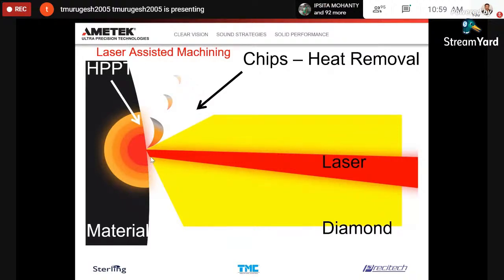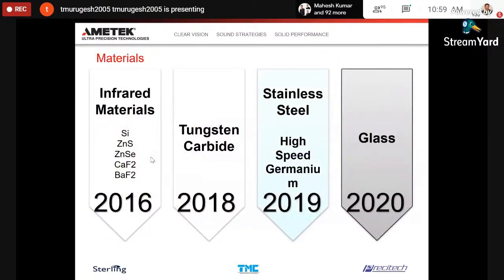So you may ask, Murugesh, when we use laser on this material, does the material property change, or does the figure or shape of the component change? The answer is no, because the technology is developed in such a way that it creates almost no heat. Definitely there will be some heat, but it is almost no heat, keeping the material intact. There is no deformation of the material property, no change in the shape of the material. So this is one of the advantages of using laser assisted machining. So how did we extend our applications? Infrared materials: zinc selenide, silicon, calcium fluoride, zinc sulfide, barium fluoride.